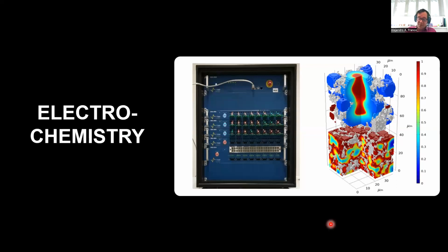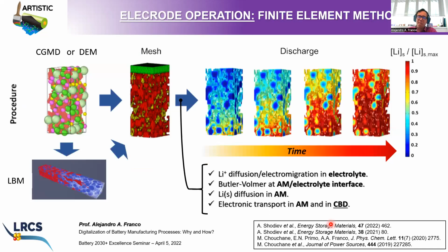The last step towards the digitalization of this battery manufacturing process is, of course, the electrochemical performance of these virtually generated electrode microstructures from the manufacturing simulations. Here you see the entire workflow. We start from the simulation of slurries and also the calendering, using CGMD, and the drying as well, using coarse grain molecular dynamics and discrete element method. We can use the lattice-Boltzmann method or the surrogate version of the LBM using machine learning to predict the electrolyte infiltration.